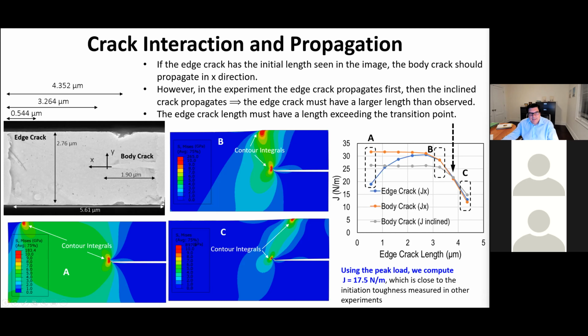Similarly, the edge crack, initially as the crack extends, increases, but then it starts going down and becomes the same as the major crack. But when you look at the inclined crack, you see at some point there is a crossover, meaning that the applied J of the inclined crack is larger than the J of the other two, and that's what we think was the geometry of the sample that triggered that propagation. And if you assume that that's the case, and you look at the maximum load, you predict the toughness for that inclined mixed mode crack.